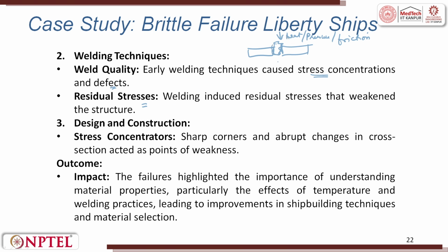So, when we apply heat, there is non-uniform shrinking. The welding-induced residual stresses weakened the structure. The design and construction: stress concentrators, sharp corners, and abrupt changes in cross section acted as points of weakness. The outcome is, the failures highlight the importance of understanding material property, particularly the effect of temperature and welding practices, leading to improvement in shipbuilding technique and material selection.